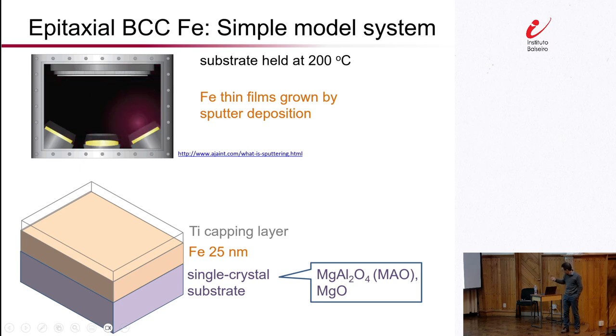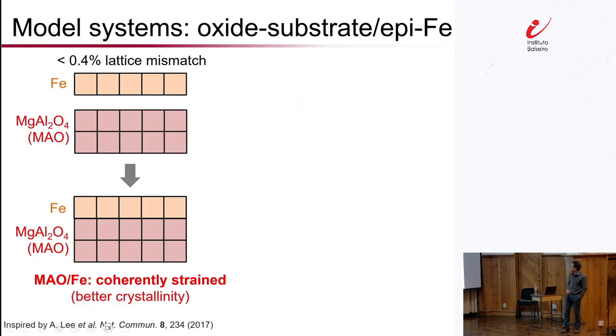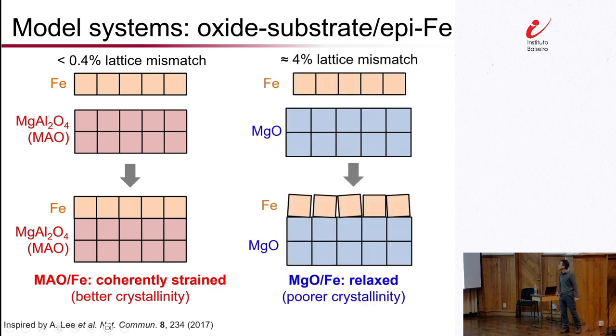Okay. Now, you might have noticed that we have two types of crystal substrates, and you might be wondering why. Here's the answer. This one substrate, what we call MAO, short for magnesium aluminum oxide, is a type of spinel oxide. This material actually has a nice degree of lattice matching with BCC iron, such that the resulting film is nicely coherently strained. So it tends to have very few defects, good crystallinity. Now, on the other hand, when we grow iron on top of magnesium oxide, we have a much larger degree of lattice mismatch, such that although the iron film here is crystalline, it actually tends to contain quite a few defects. So this turns out to be a relaxed epitaxial film.